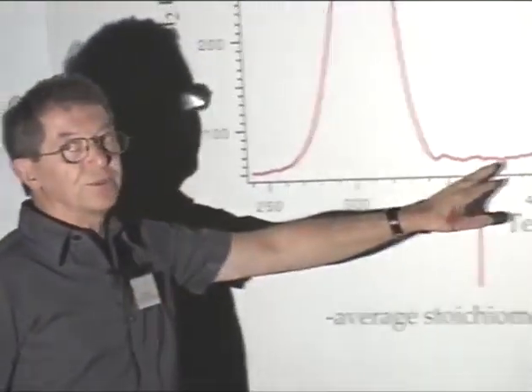Now, density functional theory calculations show as well the most stable product of methane dissociation is CH. So CH3 and CH2 are metastable with respect to CH. CH is more stable than carbon on the surface. It's more stable energetically than carbon. So why does the hydrogen come off here and leave carbon? Because the hydrogen is going to form H2 in the gas phase. So that last step is entropically driven, not energetically driven.